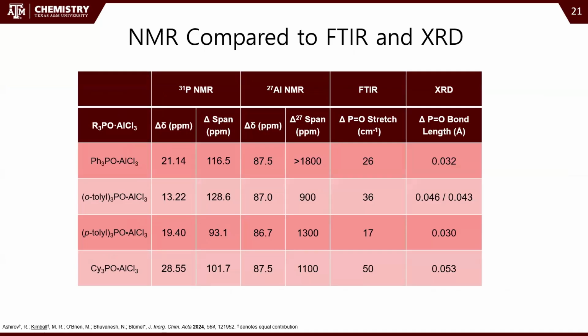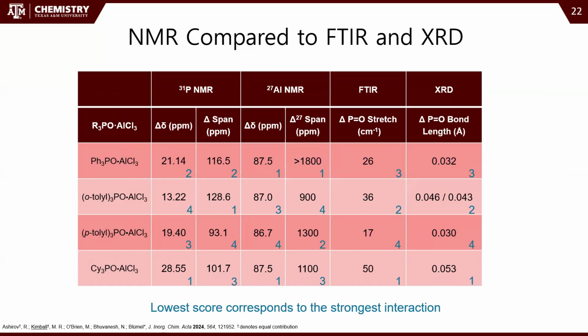Okay, we also collected FTIR and X-ray diffraction. My coworker Raheem collected these, and all of these tell us something about the strength of the interactions. So FTIR and X-ray diffraction agree across the board, of course, because they're measuring the same thing, the PO bond, right? So aluminum and phosphorus NMR are measuring the shielding environment around the nucleus, and so there's some disagreement about, okay, if you have the strongest adduct, then you should be pulling away density, and so you should see the bigger shift with the strongest adduct. But for example, the FTIR and X-ray diffraction say that's 2, and that's 4 according to phosphorus NMR.